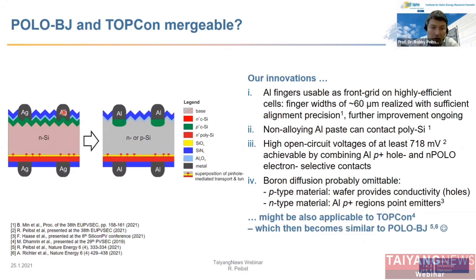But as we've shown for the POLO back junction cell, you can use aluminum also as a front grid. You can print narrow lines and you can align them to the laser contact openings. So this could also be an interesting option for a TOPCon cell. Also, the non-alloying aluminum paste applied for the aluminum metallization of the polysilicon on the rear could be an attractive option for a TOPCon cell.